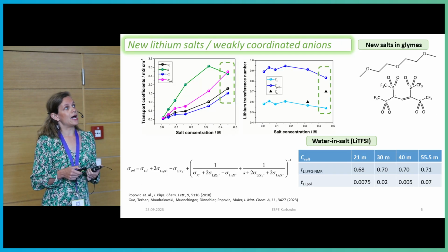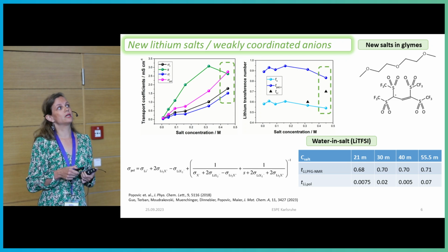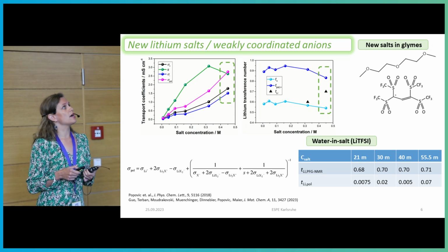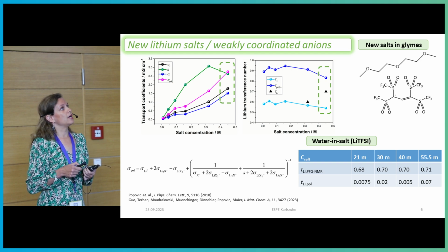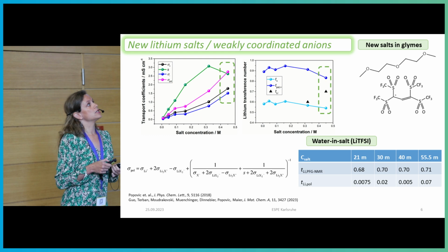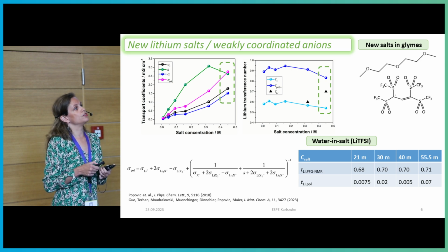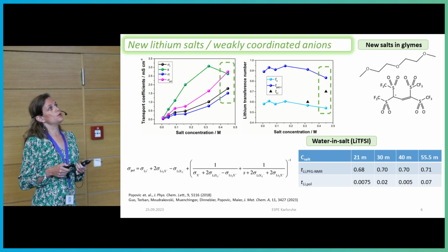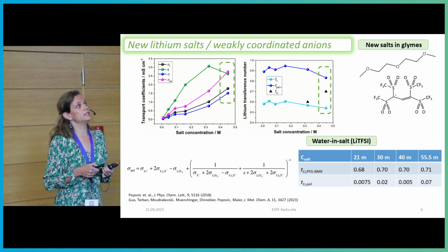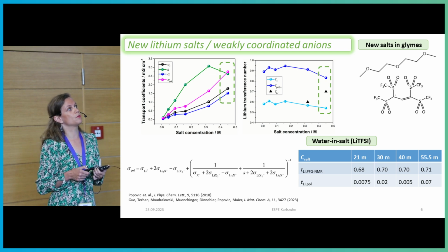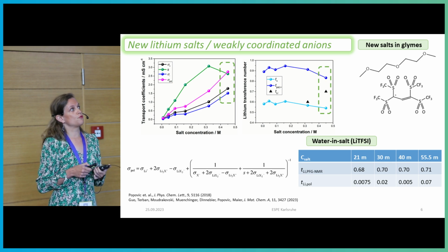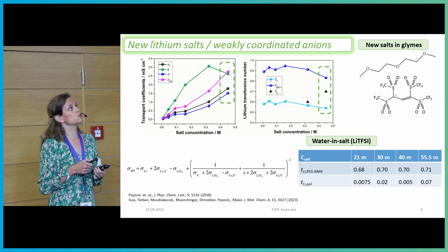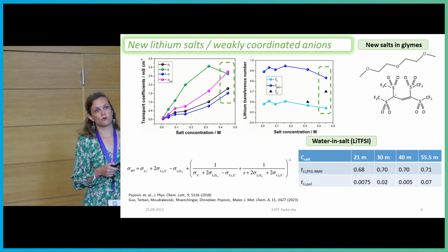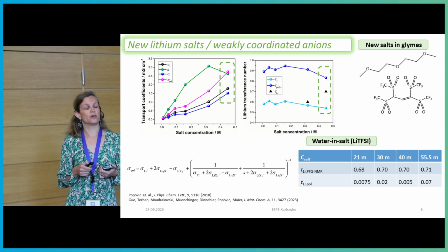One is glyme electrolytes with a very specific, very bulky anion. And in that case, we see, as expected, that ion pairs dominate the transport at all salt concentrations. But what is also unexpected is that in this case, the lithium is also more conductive than the anion. And at the end of the day, we see that in this specific liquid electrolyte, at these relatively low concentrations, we can have actual transference numbers that are really, really high, which is related first to the higher mobility of lithium versus the anion, but also due to this very high contribution of the ion pairs. So that is possible in the liquid, but under very specific conditions.